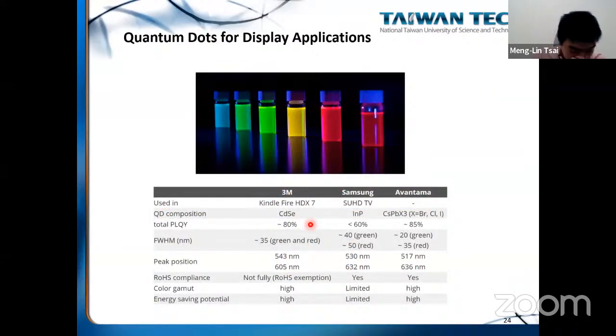Recently the commercially used quantum dot for display application is indium phosphide. It all started when 3M developed the first quantum dot display, the Amazon Kindle Fire e-book, using cadmium selenide quantum dots. You can see the quantum yield of this material is very high, with a very narrow emission width of 35 nanometers. But one thing that's not good about this material is that it's toxic because of the cadmium element, right? So it will be restricted. It's already been restricted in the European Union.